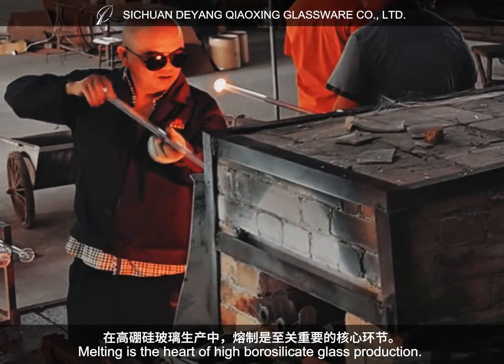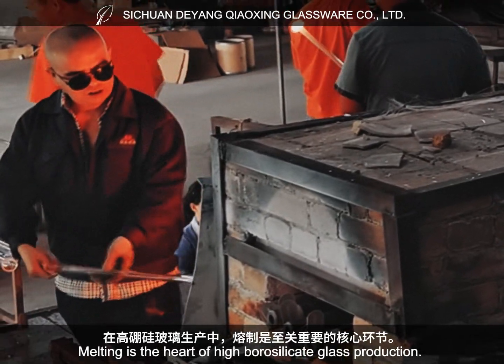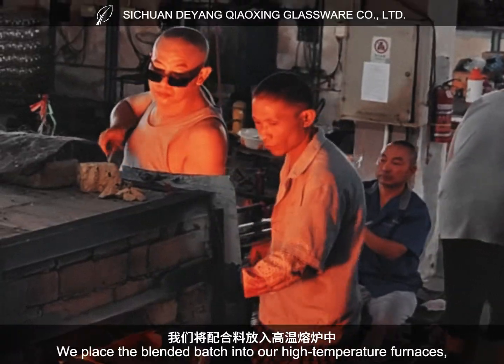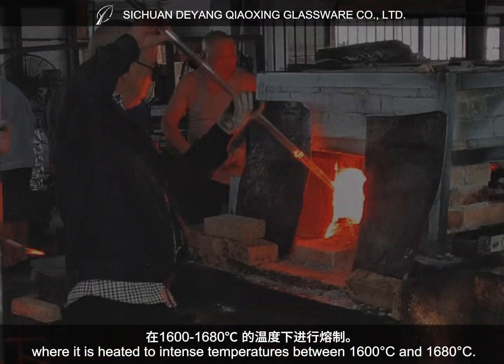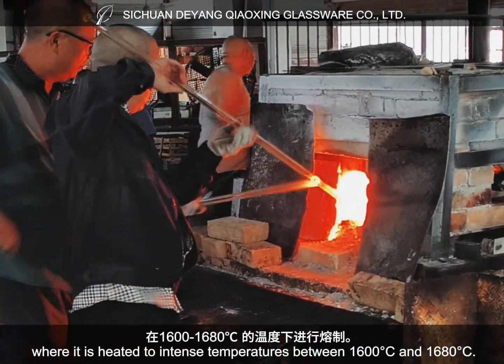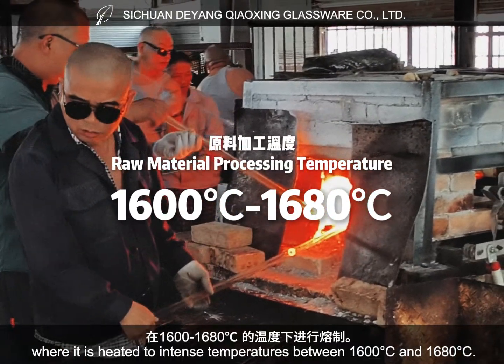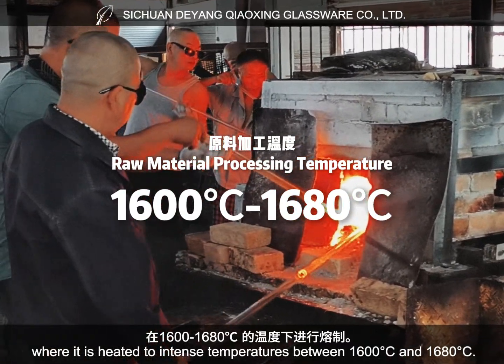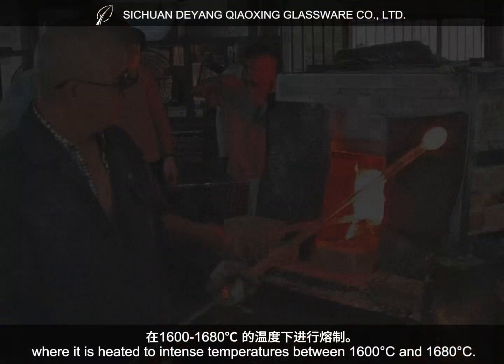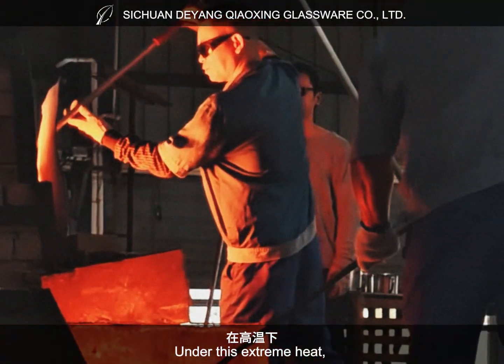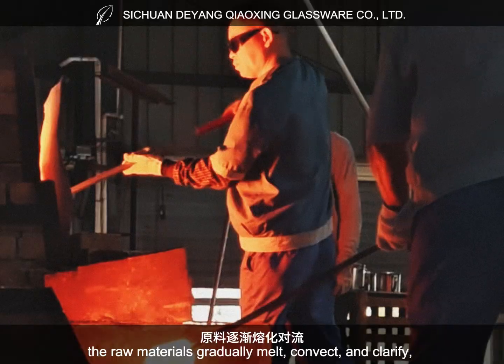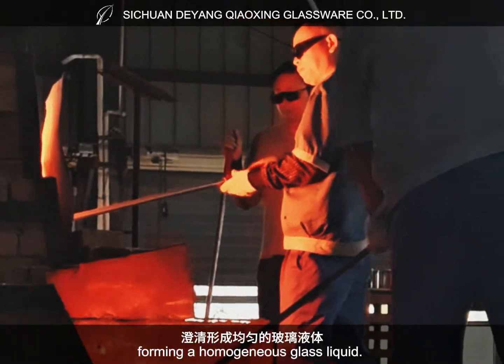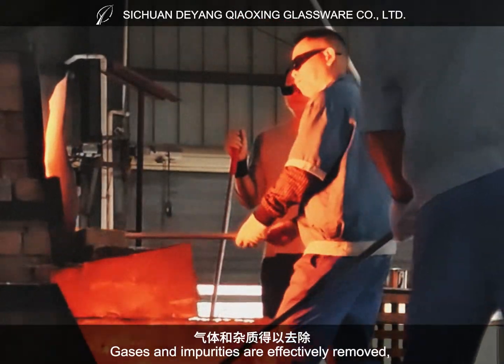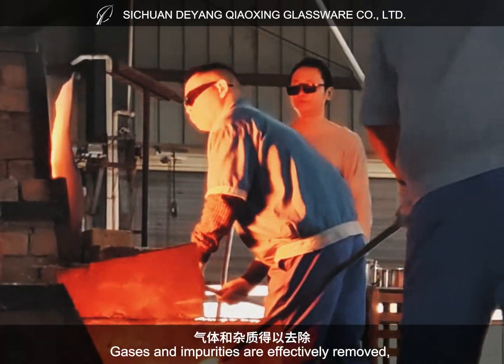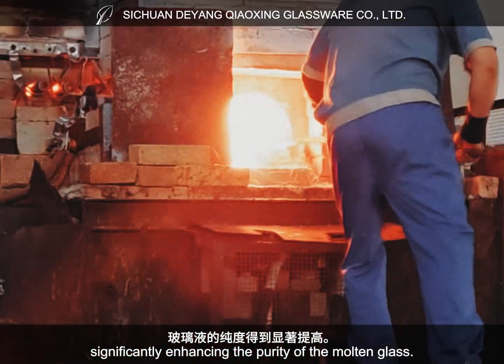Melting is the heart of high borosilicate glass production. We place the blended batch into our high-temperature furnaces, where it is heated to intense temperatures between 1,600 degrees Celsius and 1,680 degrees Celsius. Under this extreme heat, the raw materials gradually melt, convect, and clarify, forming a homogeneous glass liquid. Gases and impurities are effectively removed, significantly enhancing the purity of the molten glass.